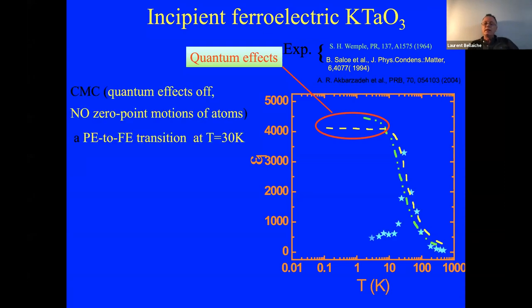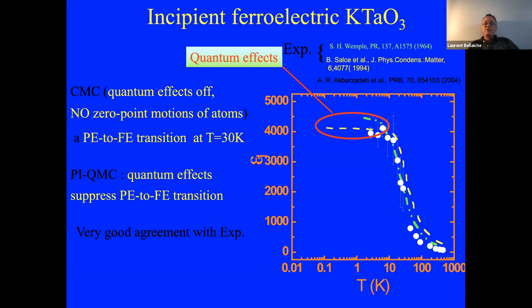The first simulation we did is classical Monte Carlo. Basically, no quantum effects. And if we do that, we found a paraelectric to ferroelectric transition at 30 Kelvin. So a peak in the dielectric response and polarization appears, which is not what experiments see. And now we put quantum effects into play. This is indicated by this dotted symbol. And suddenly, polarization disappears. Suddenly, no peak in the dielectric response and good agreement to experiment. So this shows that indeed, in this system, it's the quantum effects that are killing polarization and making this dielectric response very big at low temperature.